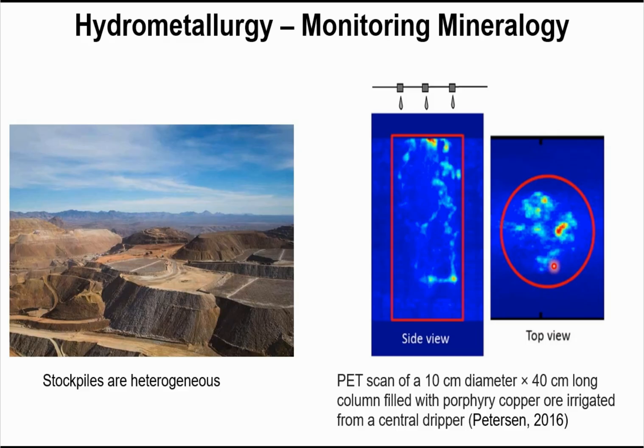Heap leach operations, one of the challenges with them is they are notoriously heterogeneous. So if you imagine a heap over here that could be tens to more than 100 meters high, and we look at a side view versus a plan view, in the side view, what you can see is that there are channels that allow for the preferential percolation downward of the lixiviant. What mining companies try to do is they want the lixiviant to percolate through the entire heap and react with all of the oxide and sulfide copper minerals they can come in contact with.